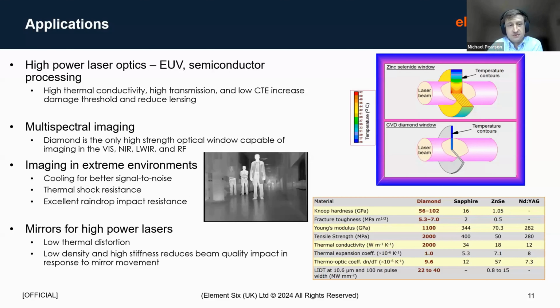Yeah, so imaging in extreme environments. As I was saying, if we, for example, are trying to do IR imaging through a hot window, you have a poor signal to noise ratio. In the case of a sapphire window, there's not a huge amount you can do about that. You could try and implement a cooling system, but the low thermal conductivity of the sapphire is unlikely to yield much benefit. In the case of diamond, if you have well-designed cooling, you can keep your window temperatures pretty low, increase your signal to noise ratio, and get better imaging through that window than with other common materials.